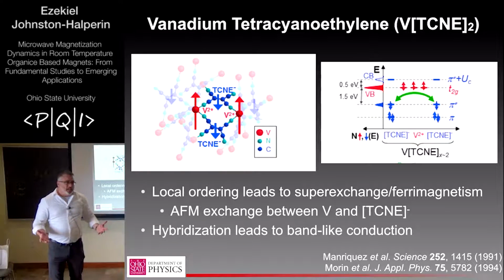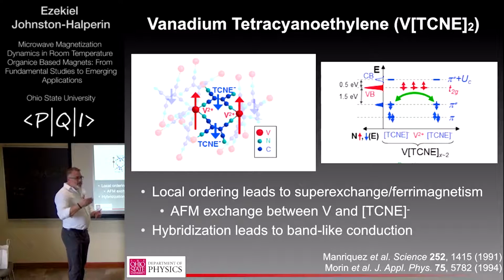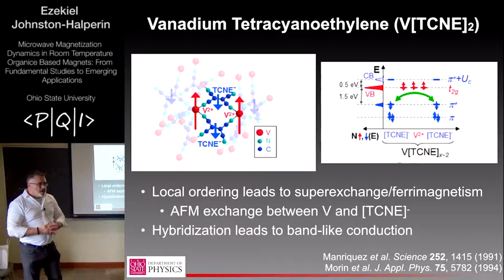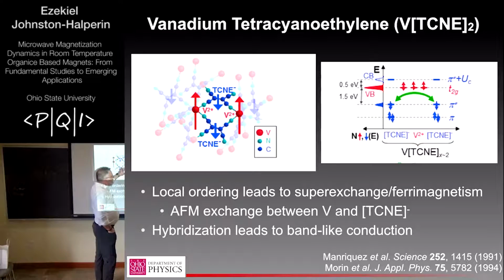So it's in this regime of many organic semiconductors where you can think of it as either a pretty good hopping transport or a pretty terrible band transport. But it's also potentially ambipolar. So this is what this is supposed to indicate, and again, some of this is received orthodoxy from prior people in the field, and we're still in the process of sorting out how much of this we believe and how much we don't. But if you want to call this the HOMO and this the LUMO, the conduction band effectively sits on the TCNE sites, in this pi star orbital, but it's energy shifted from this state by the Coulomb occupation energy. And then exactly where these t2g orbitals sit in this gap is a little bit of guesswork.